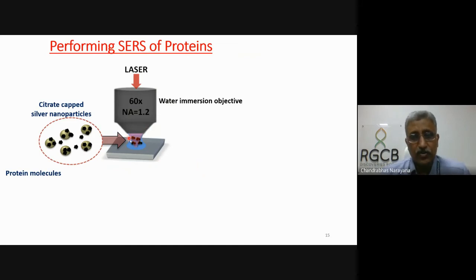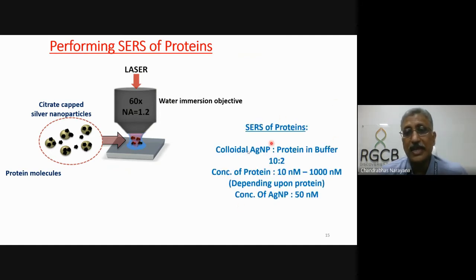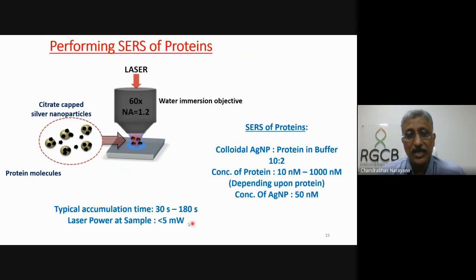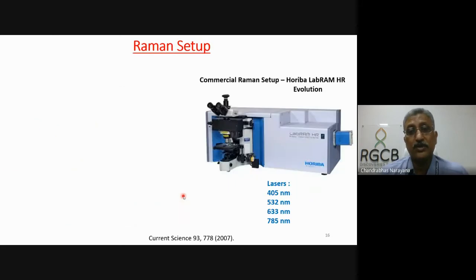So whenever we are doing a biomolecular system, what we do is we incubate the biomolecule with the nanoparticles and keep it in the microscope in the liquid itself. Otherwise, the protein will denature. So this is the kind of concentrations which we use. And typically, we use about 30 seconds to 3 minutes as the accumulation time. And our laser powers, we try to keep as low as possible, below 5 milliwatts.